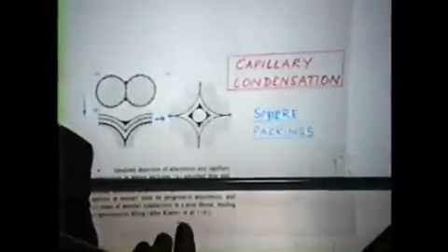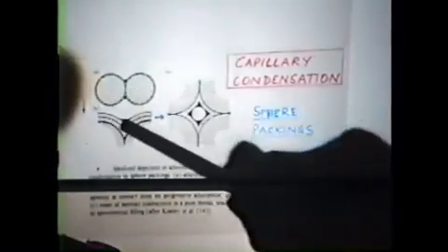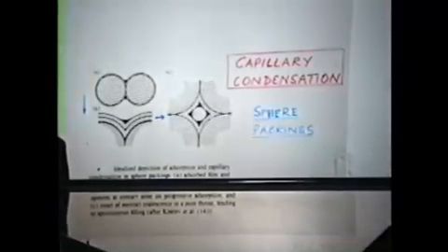This is based on the structures put forward by Karnikov. But if one has a silica gel made up of monodispersed spherical particles, one has a relatively uniform pore structure in the system. On the basis of what was proposed way back by Kiselev, one can envisage, in the ideal case, capillary condensation occurring as shown here. In micropores, this mechanism breaks down.